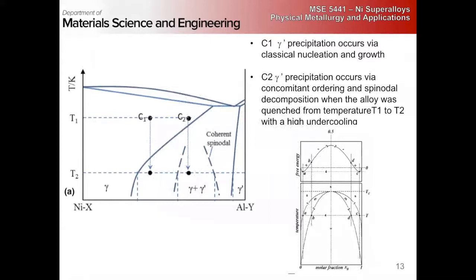So gamma prime, depending on where we are and what our composition is and where we're cooling from, can either occur by a classical nucleation and growth mechanism or by a spinodal mechanism, right? So either nucleation and growth or local ordering and phase separation, right? Typically, the higher the alloy concentration, the more likely we are to form by a spinodal mechanism rather than nucleation and growth. Okay?